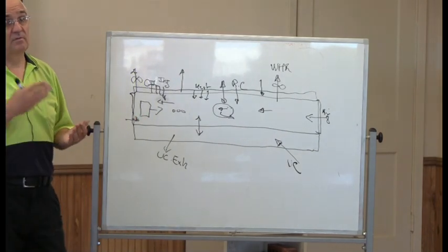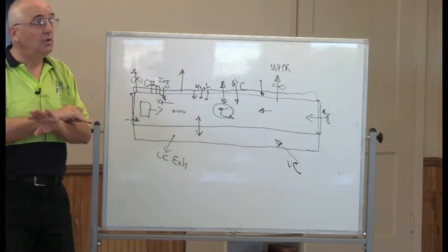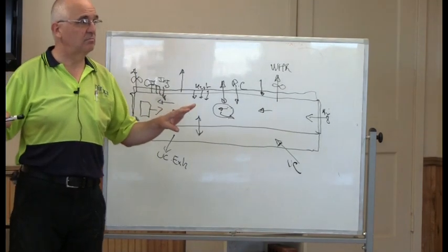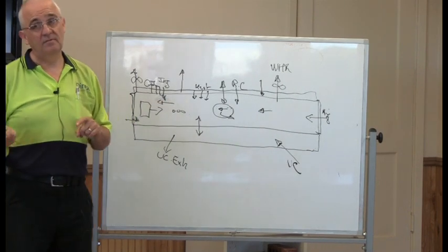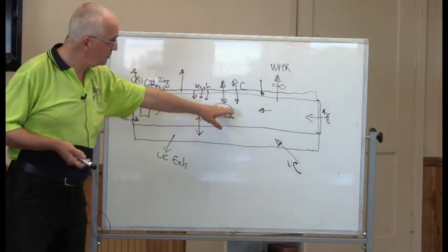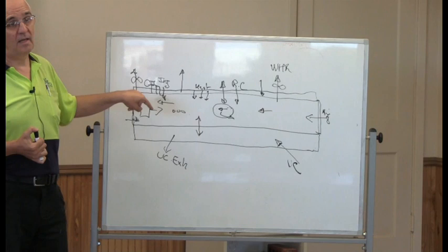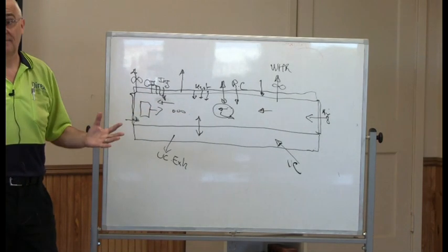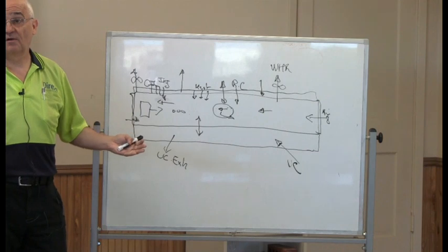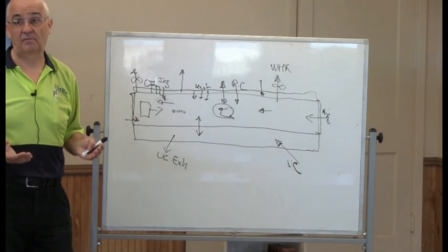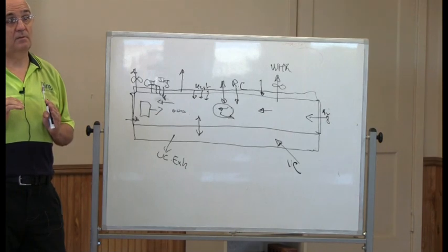They installed the booster burner, they changed the kiln to the proper operation. No change on the gas usage. No more, no less. Then the next step they did was, because the kiln was running in the proper direction, they could work on their burners. And their burners were cheating everywhere. But guess what? When you remove the cheat, at the last visit, we found a change of gas usage of up to 9% less gas. And they have just worked on half of their burners so far.